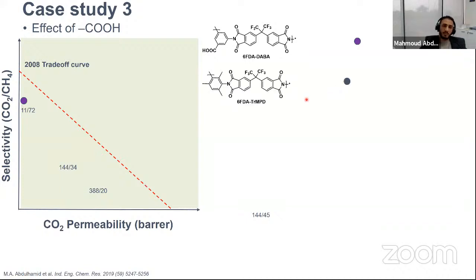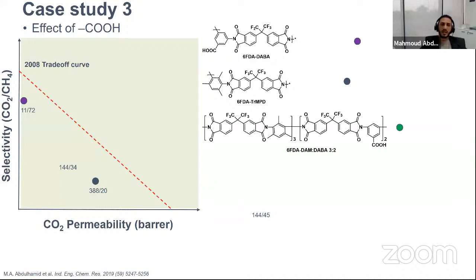There is another polymer which is not functionalized. That has also been prepared and studied for gas separation, and it is performing in this region here, where it has very high permeability but moderate selectivity. So researchers have tried to develop a new type of copolymer where you mix this one with this one in a 3:2 ratio, and you achieve a performance in between, with a good permeability and a good selectivity at the